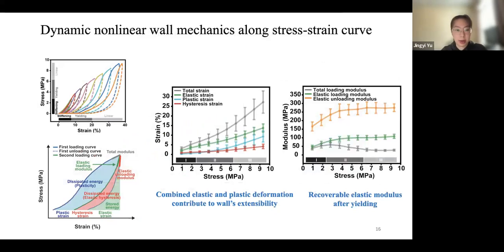And in the interest of time, I will not get into all the parameters here, but only point out two major observations we found. First, in the strain analysis, we see that even after the initiation of the plastic deformation, and you can see the blue curve, which is the plastic strain, starts increasing, the elastic strain continues to increase after the yielding starts, showing that the extensibility of the cell wall is a result of combined elastic and plastic deformation.